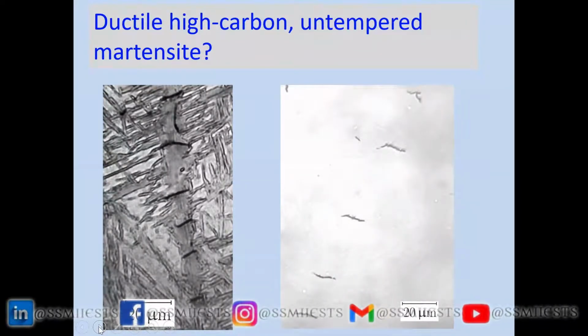Okay, so what we need to do is to get the austenite grain size to something of the order of 1/4 of a micrometer. Now, how on earth can you get an austenite grain size in a mass-produced material, which will have a reasonably low carbon concentration, yet have a strength of 2 gigapascals and be weldable? So if you go to the next slide,